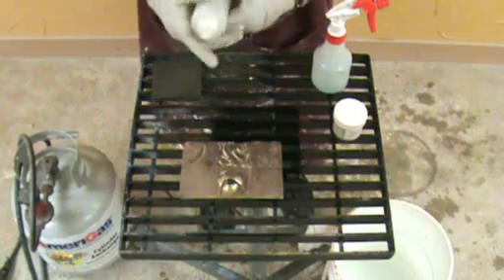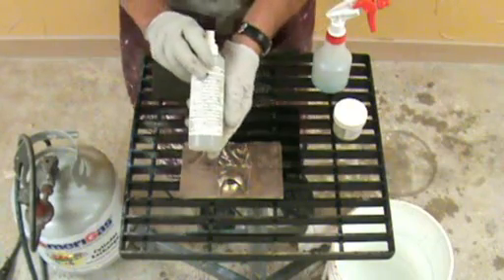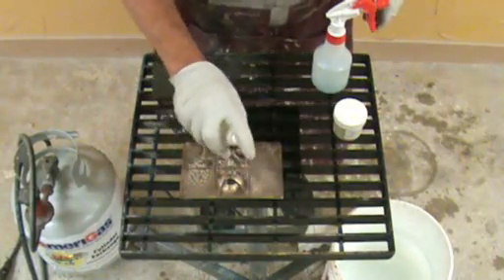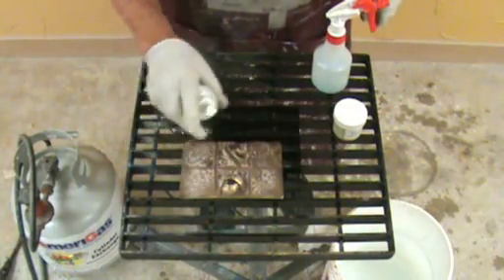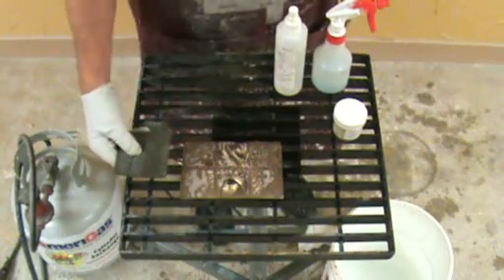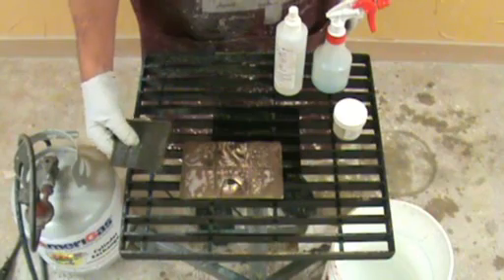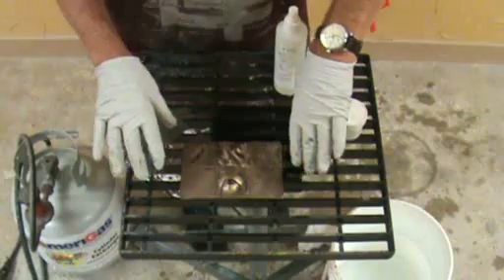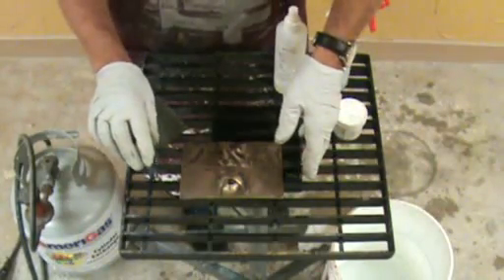First we'll clean it with industrial metal cleaner. You want to leave this on for about a minute and then clean it off. Generally I'll use a Scotch-Brite — this is a grey Scotch-Brite as opposed to a green or red. Remember all of these base patinas have to be rinsed thoroughly.